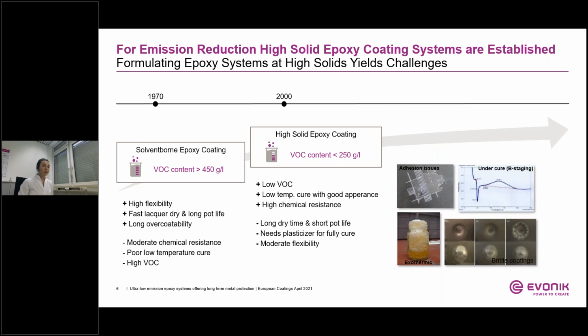To ensure that the high solid system can react fully, the curing agents and the epoxy resin are typically formulated with additional plasticizers such as benzyl alcohol. Those modifiers are also essential components to improve system compatibility, dry speed, and adhesion. One drawback is that under certain conditions, those plasticizers have the potential to leach out during the service life of the coating. This can affect the mechanical properties of the coating and can lead to reduced flexibility. Consequently, the potential to lose performance is increased over time.